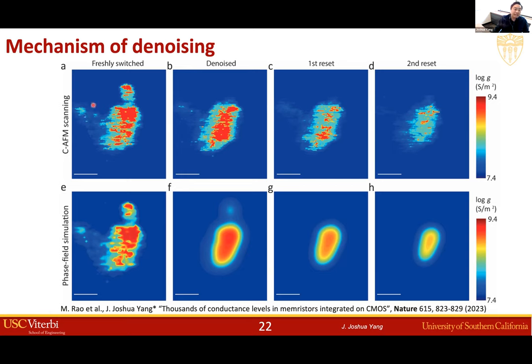And fortunately, those are also metastable phases and they can be removed by using a relatively small voltage, smaller than the threshold voltage to switch the device. And you can use such a relatively small voltage to denoise it by removing those. And this is the denoise process. And if you want to switch the device to a more resistive state, you can just use a voltage over the threshold, then the channel or the filament becomes smaller and smaller during the switching.